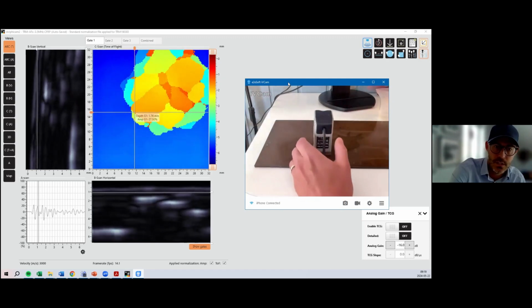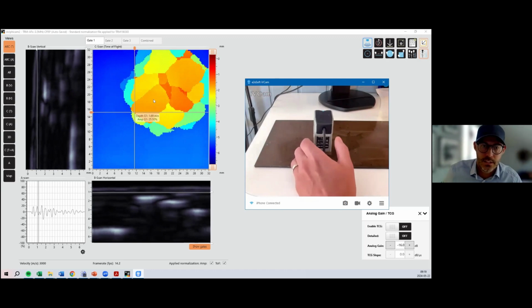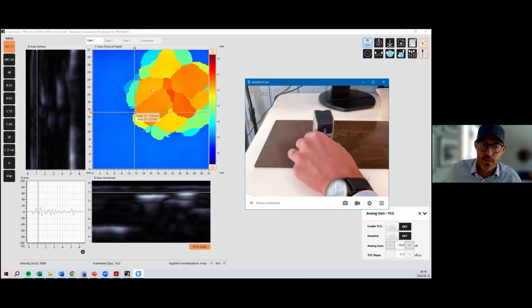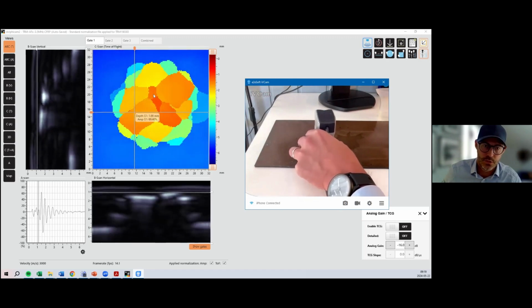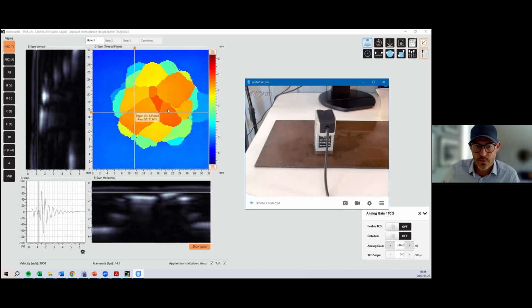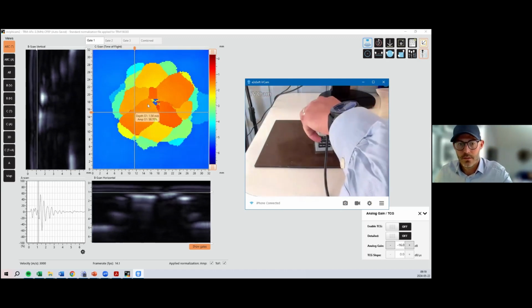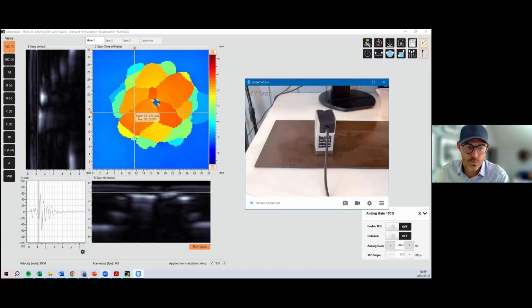And as you can see, the layers are 90 degrees or 45 degrees on top of each other. Each layer of carbon fiber has kind of broken, and that's why you see this pattern. So the ones of you that are familiar with composite production and how composite or carbon fiber is built up, this is what you see. So very easy to use.